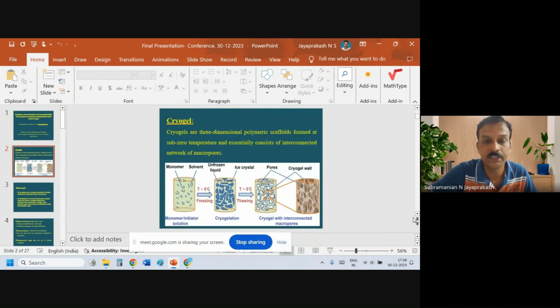So before getting into the subject, let me tell you what cryogels are. Cryogels are three-dimensional polymeric scaffolds formed at sub-zero temperature and essentially consist of an interconnected network of macropores. Here in the picture, you can see the process of making cryogels. It starts with a monomer along with initiator solution, and you do the freezing below 0 degrees centigrade, which leads to cryogelation, followed by thawing. And this thawing will make cryogel with interconnected macropores.